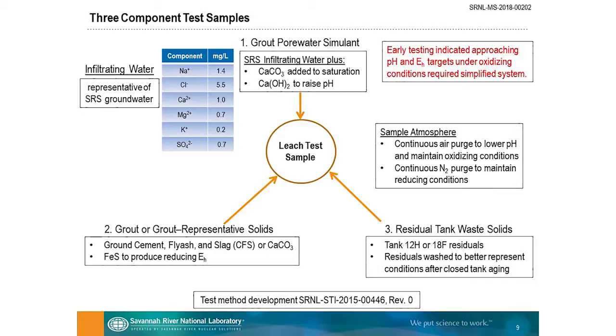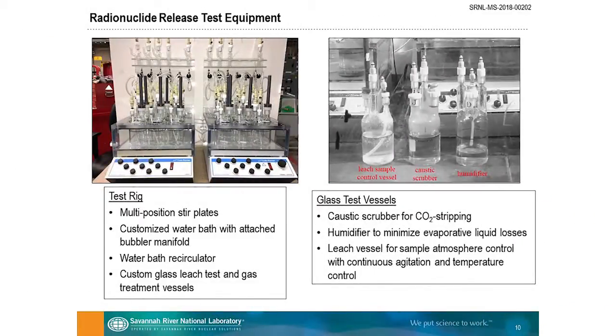We then had to control the atmosphere to produce the oxidation reduction potentials that we were targeting. For the oxidizing samples, we purged with air, typically stripped of CO2 because CO2 will affect the pH. And for the reducing samples, we purged with nitrogen. So I don't know how well you can see these pictures, but that's a picture of the equipment. In order to control the atmospheres in the sample, we needed a series of vessels to either strip out CO2 or humidify the gas so that we didn't continually lose sample due to evaporation.